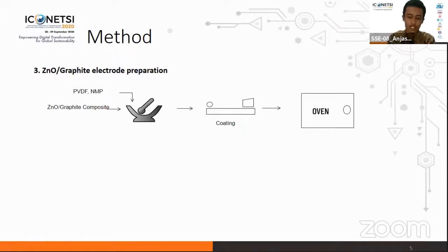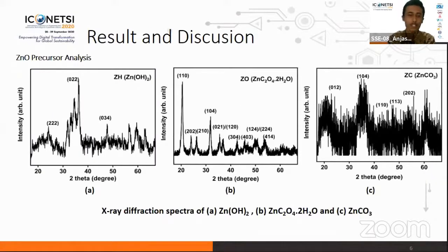The ZnO samples were characterized using XRD and mixed with artificial graphite to obtain a ZnO-graphite composite anode via solid state grinding. Results and discussion. These figures show the XRD spectra of the ZnO precursor obtained from various precipitants. Figure A displays the ZnO precursor via the hydroxide precipitation route. Figure B shows the ZnO precursor obtained via oxalate precipitation, and Figure C presents the XRD spectra of the ZnO precursor from carbonate precipitation.